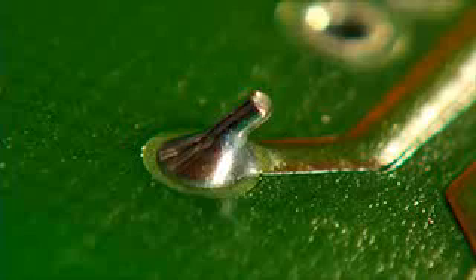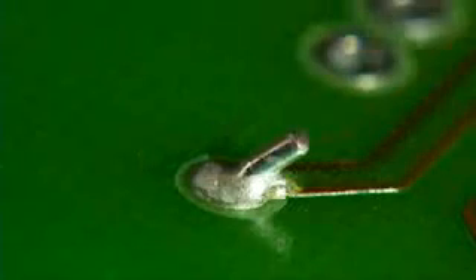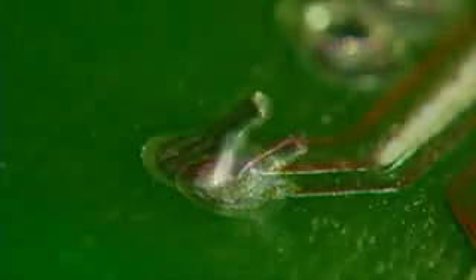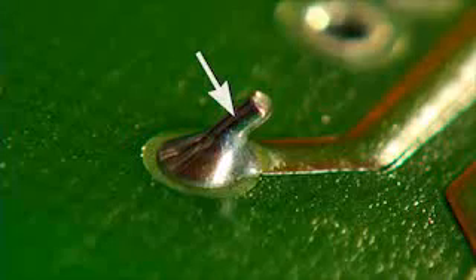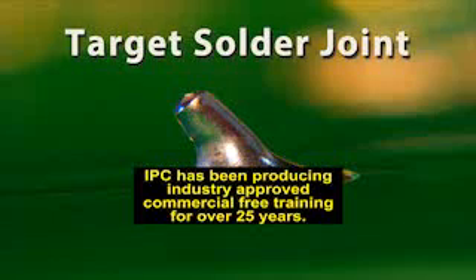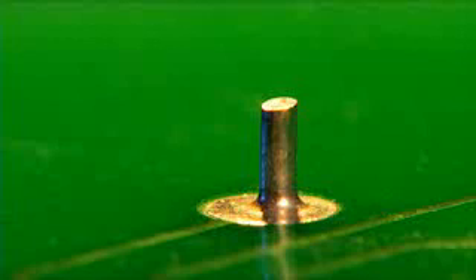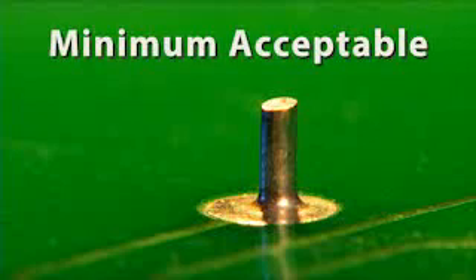The texture is smooth and shiny for tin lead and may be grainy for lead-free. The outline of the lead is visible beneath the solder. The amount of solder here is just about perfect. These are good examples of target through-hole solder joints. Here's one now with a little less solder. You can see that the wetting is still good and the coverage is even. The fillet is concave. This solder joint is perfectly acceptable, even though there is less solder in the connection.